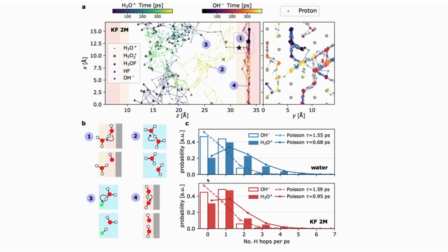We can also analyze this more cleanly. The initial state is 1 here, the first step of this reaction. This happens by a chemically absorbed water donating a proton to a physically absorbed water. That's 1, and then it forms a hydronium. This hydronium then diffuses away. It does not diffuse by the typical translational diffusion of water molecules, but via the Grotthuss proton transfer mechanism indicated in 2.